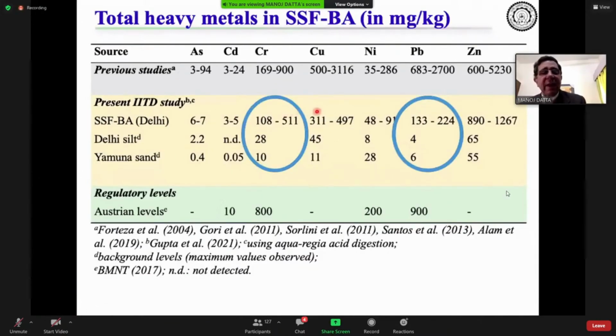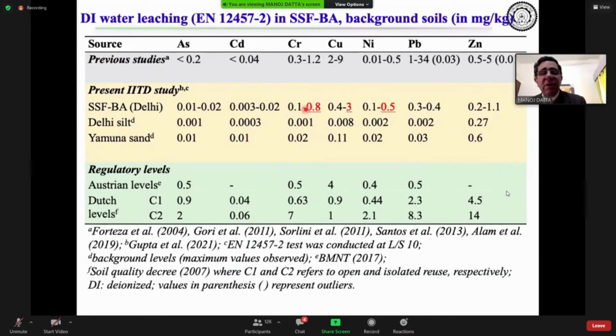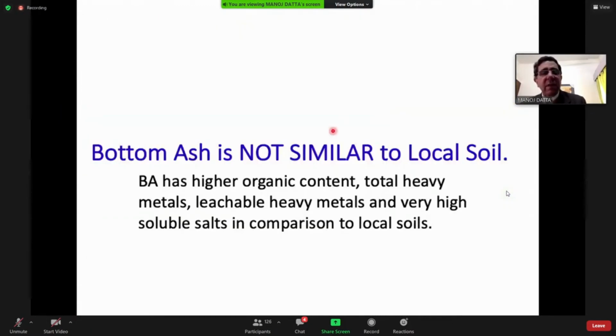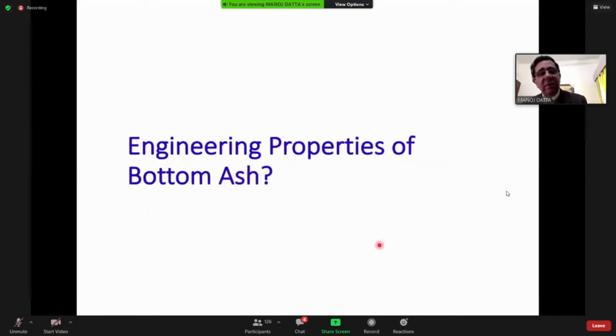And again, there are elevated heavy metals. Just look at chromium in Delhi silt and Yamuna sand, and what we are getting here. Look at lead. And again, look at the leachable metals. And so bottom ash is not similar to local soil. It has high organic content, total heavy metals and leachable heavy metals, and very high soluble salts in comparison to local soils. And another characteristic which I did not highlight is that its pH is also in the higher range, which sometimes affects the use of polyester geosynthetics.